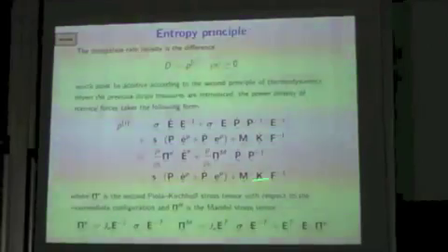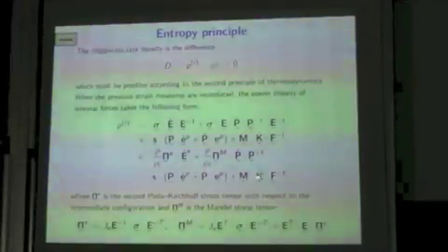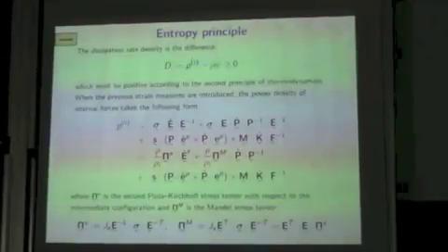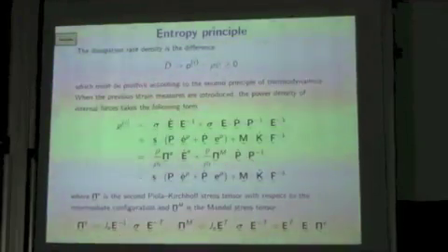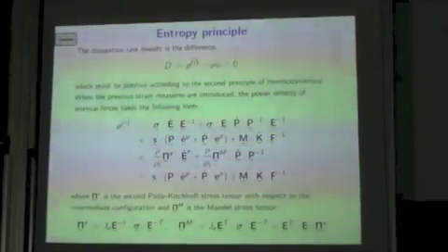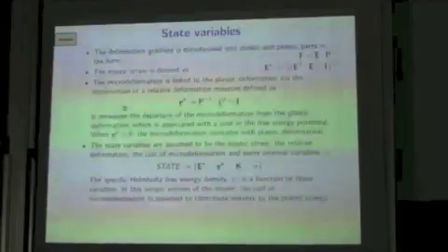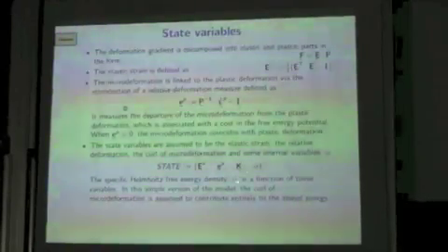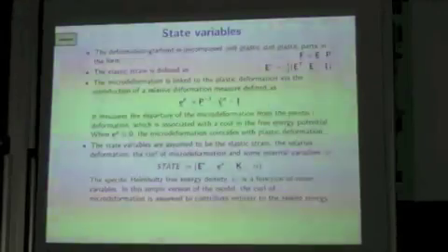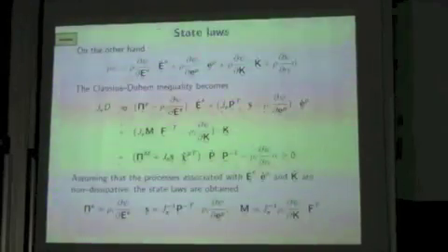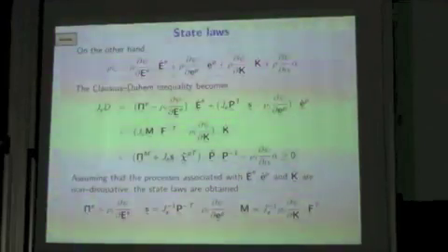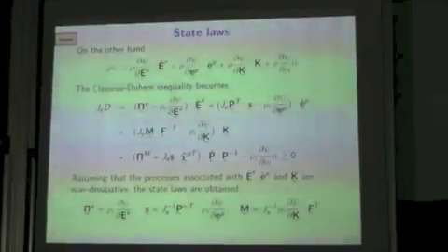You see that there is no special plastic contribution related to K. This is an assumption I state here in this simple model, that you store energy with K, with the curl, and there is no split into elastic and plastic. You can do it, maybe necessary in some cases, but in my example here, I don't need that. So really, the full K here, the curl of chi p, is used to store energy completely. Okay, though I don't go into the detail because it's standard anisotropic finite crystal plasticity.